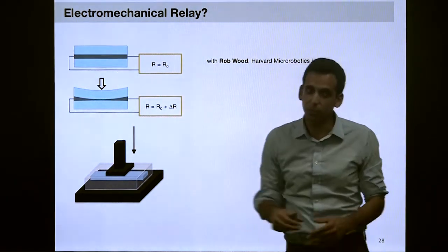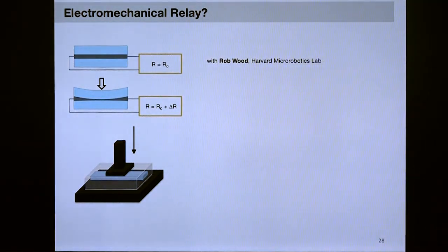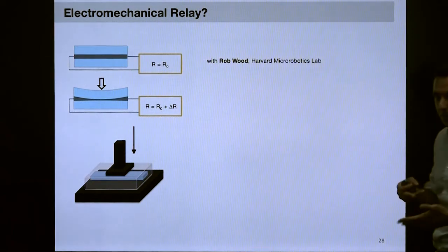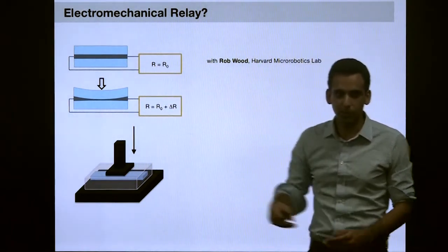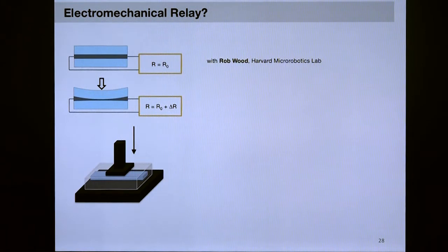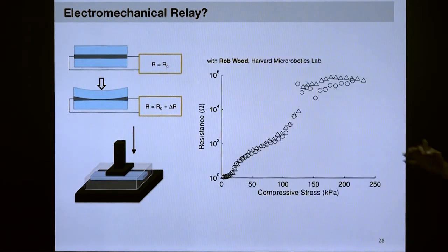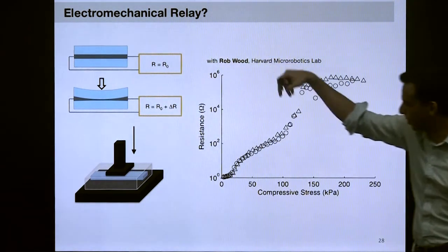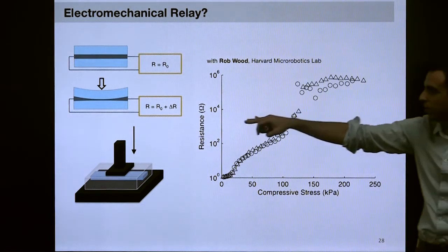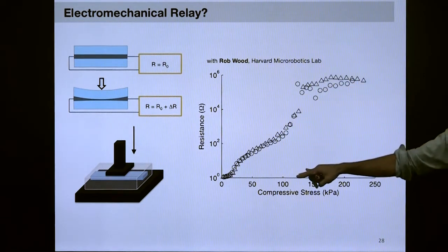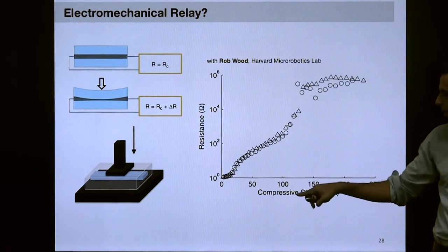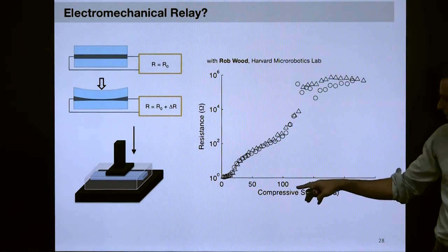So I kind of made a pressure sensor out of two of these microchannels and put them inside this elastomer, so that as you push down, the electric resistance changes. What's nice about this is that we can use linear elastic fracture mechanics to describe the coupling and relative change in electric resistance. Here we treat the channel as a crack, and just like in fracture mechanics, it opens. If you apply pressure, the crack closes.